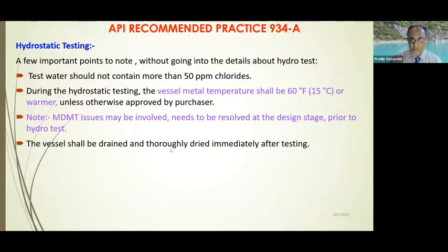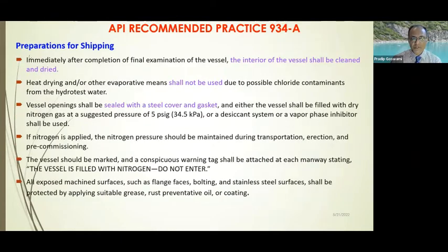And the vessels should be thoroughly drained and thoroughly dried immediately after testing. And preparation for shipping, following the hydro test and thorough drying of the vessel, has to be nitrogen filled. And all the so-called machined surfaces have to be protected by suitable grease or rust preventive oil or coating as mandated by the project specification. And that's the way they get ready for shipping.